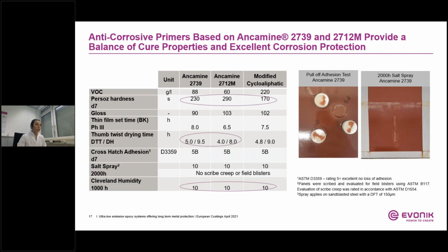Even without high level of plasticizer, coatings based on this curing agent exhibit improved pendulum hardness development versus reference. All coatings provide excellent salt spray and Cleveland humidity resistance. The cohesive failure by pull-off test on this picture indicates a good adhesion.